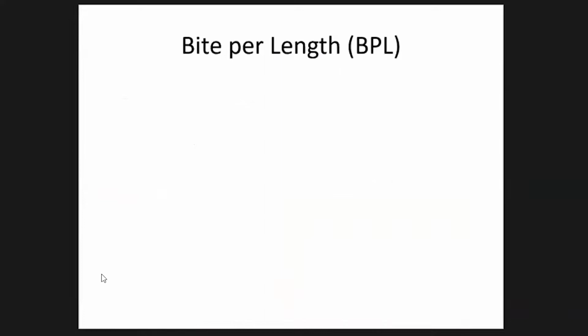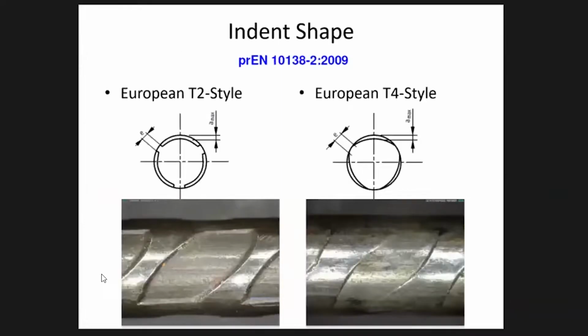The European style indents have type T2 indent, which is this one right here. And if you look at the profile of this indent, it's essentially the full depth around the whole width of that indent. How you see that is, in this north and south direction, we see a lip here. So that indent is full height across this depth.